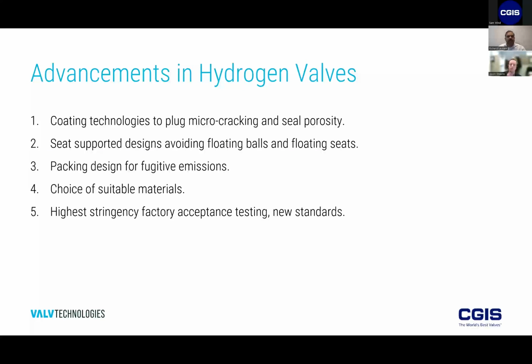So really, just to come to the conclusion, if we look at the advancements that we've seen in the design of valves, specifically for hydrogen, it really boils down to a couple of things. One is the coating technology. We talked about porosity and how to avoid that porosity. We talked about different geometries that there could be in a ball valve. Whether it's a floating design or a trunnion design, the seat supported design is perhaps the optimal out of the three geometries to assure that there's no leakage. We talked about the packing, which again, we can't just rely on standard packing. It's got to be designed specifically for hydrogen service. We talked about the general choice of materials, typically stainless steels.